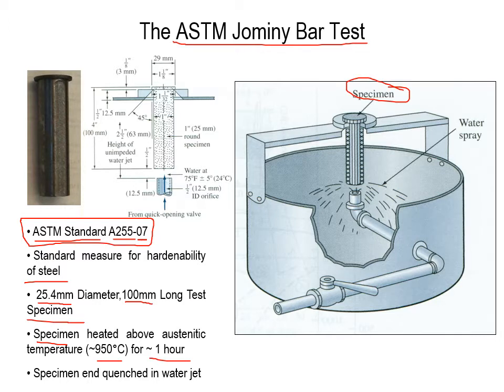The specimen is then quenched in a water jet here, and you can see the water spray coming up in order to quench our specimen. And there again is our specimen right there that meets these dimensions over here. So that's a basic overview of this ASTM standard for the Jominy bar test.